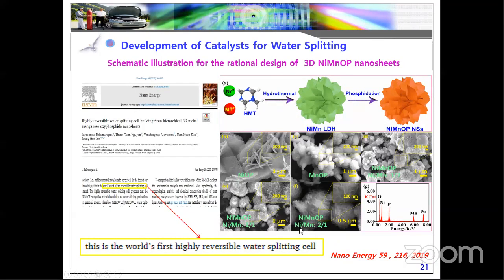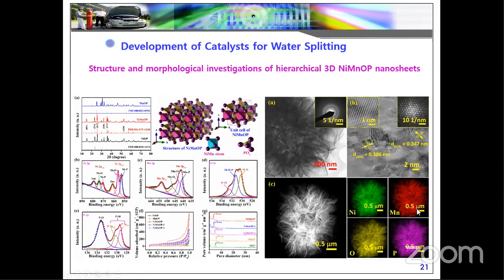Then finally we tuned the morphology with a 2:1 ratio of nickel to manganese, and we achieved hierarchical structures with a highly porous morphology. This structure was further proved by EDX analysis. The EDX analysis technique is one of the good techniques to detect the number of elements, so the presence of the elements. Structure and morphological investigations: when we are making the materials, we need to study in depth the structure as well as the morphology.